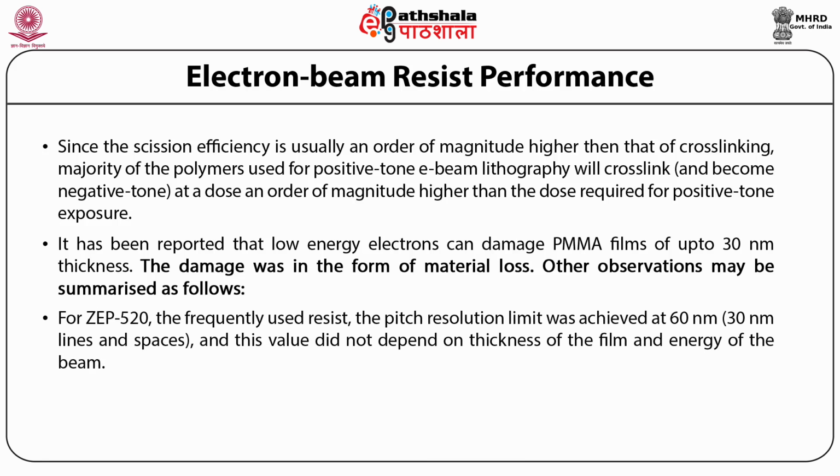First, for ZEP-520, the frequently used resist, the pitch resolution limit was achieved at 60 nanometer, that is 30 nanometer lines and spaces, and this value did not depend on the thickness of the film and the energy of the beam.